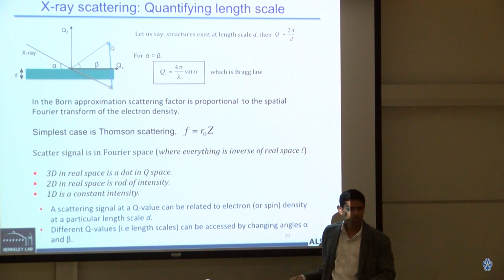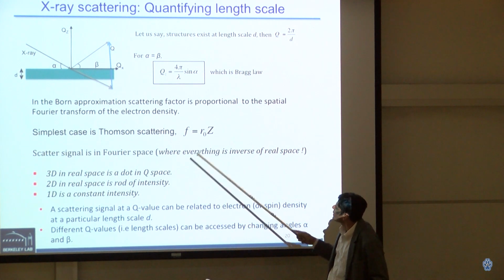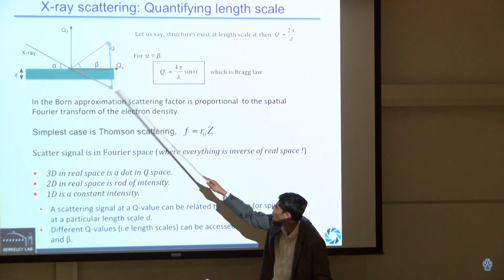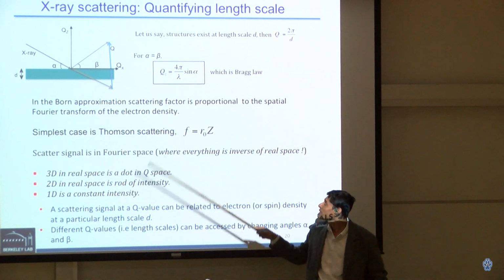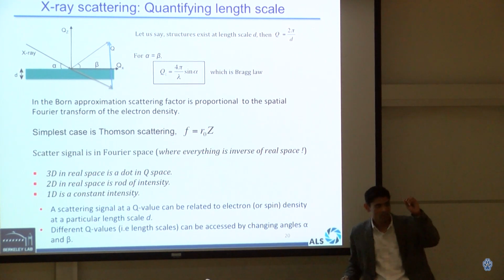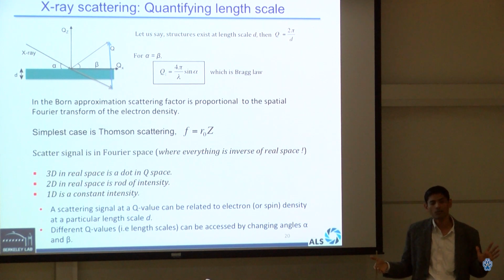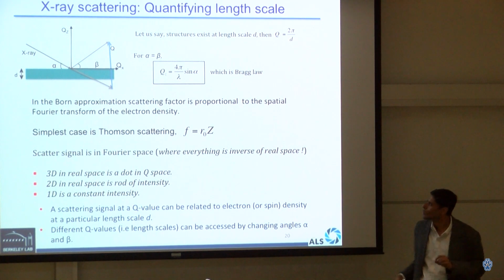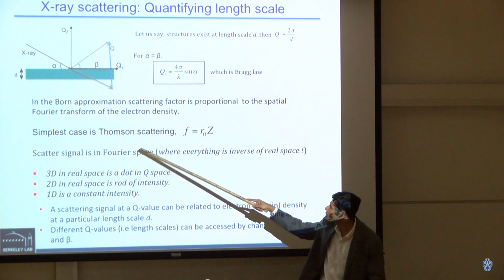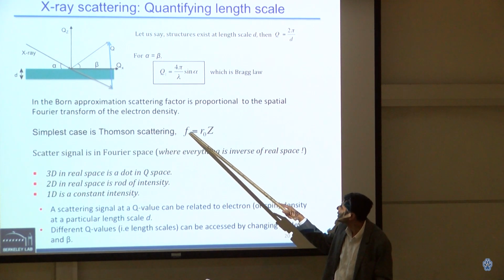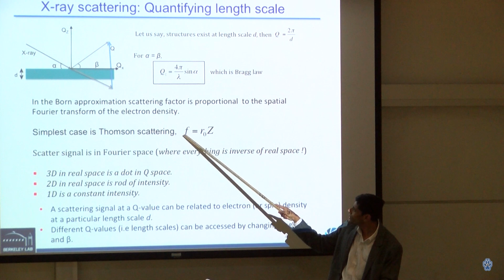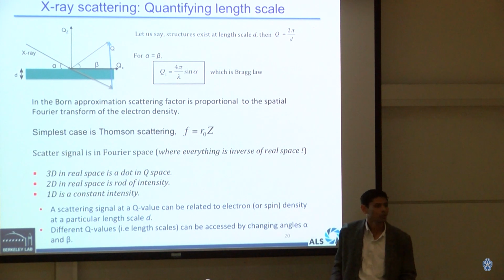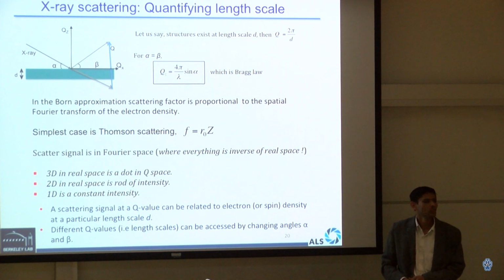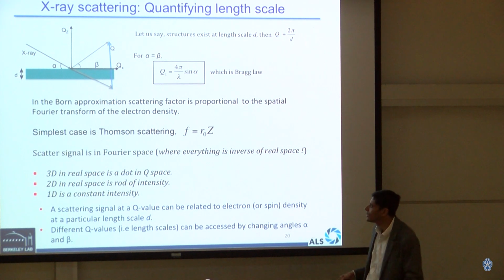So then you can go through any of your quantum mechanics books, undergraduate books, and you can easily see that in the so-called Born approximation, which is a weak scattering, this signal in reciprocal space is related to the Fourier transform of the electron density. So what does that mean? The simplest case of that, if you want I can show you, is Thomson scattering, where the scattering factor F is directly proportional to the Z number of an element. That's why aluminum doesn't scatter, that's why gold scatters more, that's why you can see bones and you cannot see tissues. There's a simple reason, just the Z number.